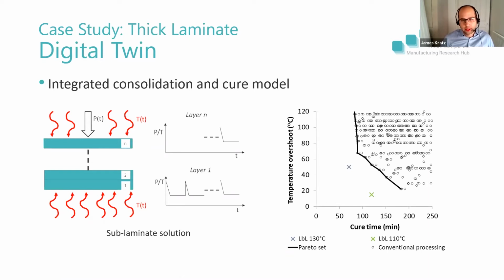Processing the component in 2 hours, not as severe an overshoot, but 15 degrees centigrade. And potentially, we have the ability to take advantage of that to achieve our target process temperature.